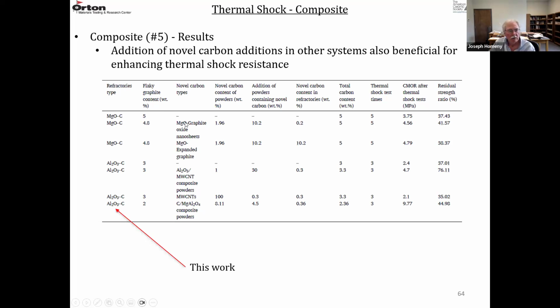And some of the additional carbon is in the form of nano sheets of carbon. And then when they look at the residual strength ratios, there's some improvement from 37 to 41. And this one is with an expanded nanographite, an expanded structure. Again, just a slight increase.